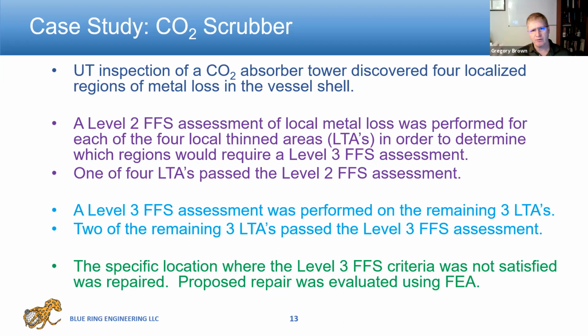For the other 3 areas, we actually did a level 3 assessment using computer modeling, what is called finite element analysis. In this case, 2 of those areas passed the level 3 assessment. They were now acceptable, but the last area did not. There was just too much wall loss, and it was actually located near nozzles. So we actually did a repair on that vessel, but we validated the proposed repair using finite element analysis. So let me show you what this looks like.